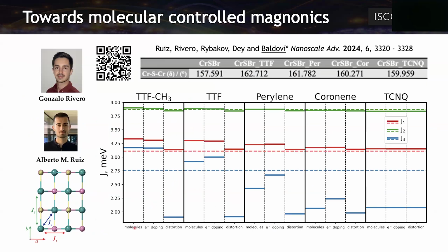Then we wanted to see what happened. Now this is the calculation taking into account the molecule. We have here the J1 that is in red, J2 and J3. And we can now add directly only doping to the unit cell. We remove all the supercell, we take just the unit cell of chromium sulfur bromide, and adding the doping, we get very similar results of J1, J2, J3. So if we know more or less the charge transfer, just doping the 2D material, we can get a good estimation of the exchange interactions in this system.